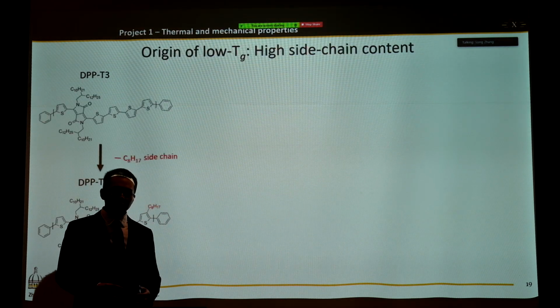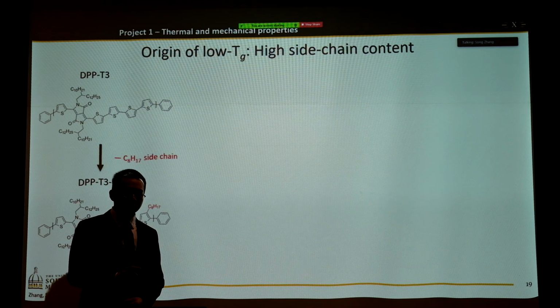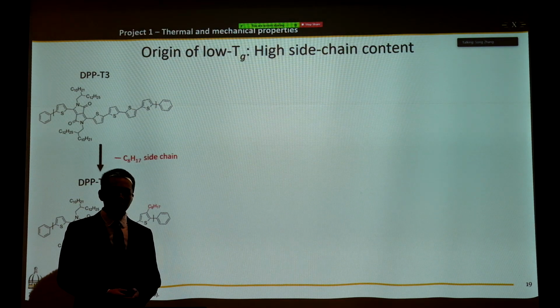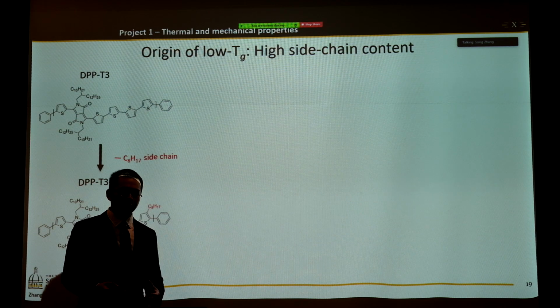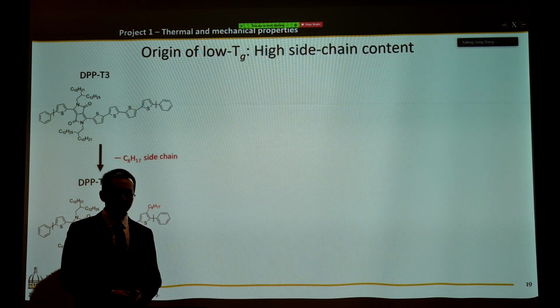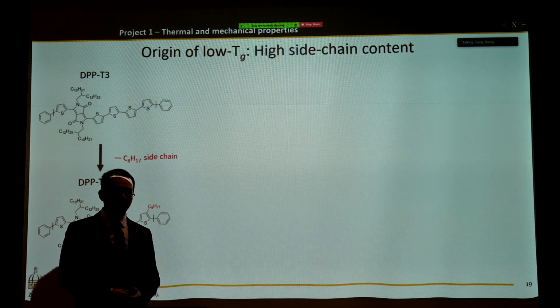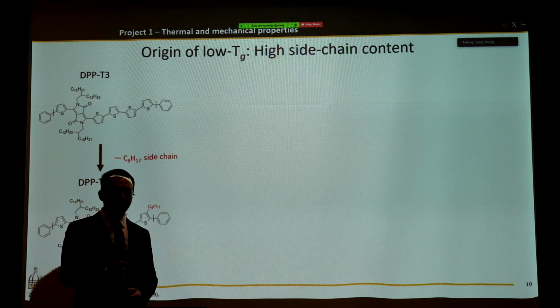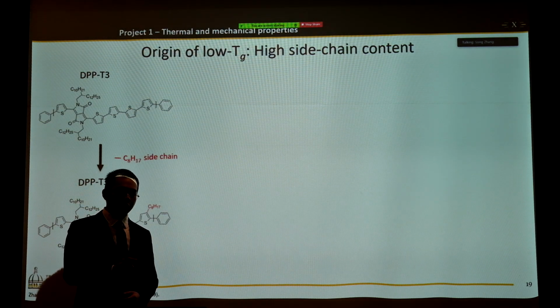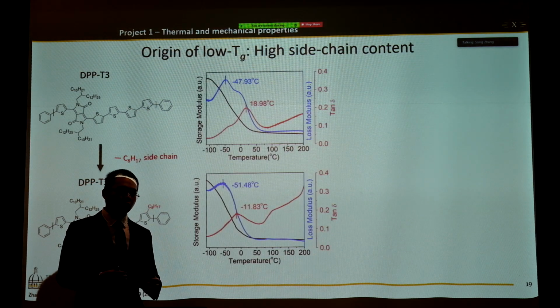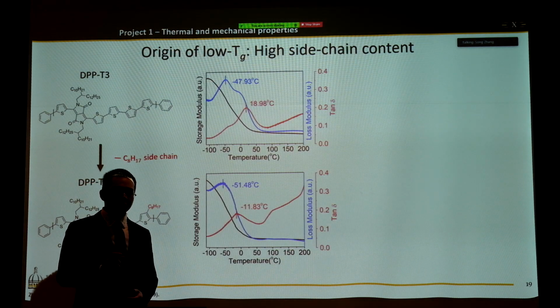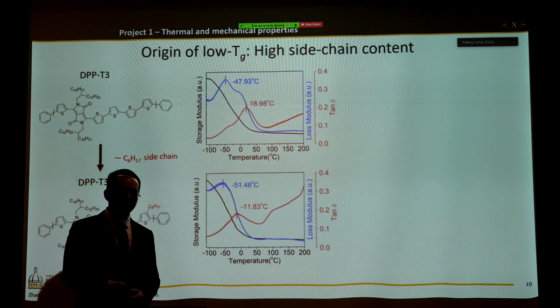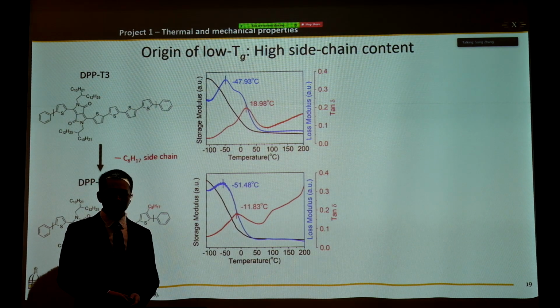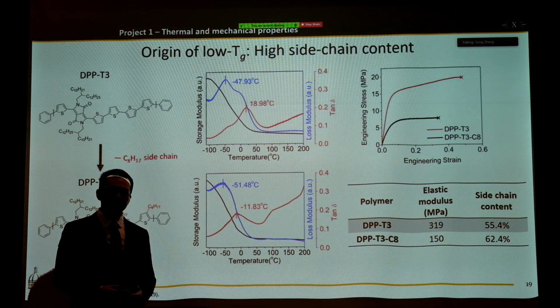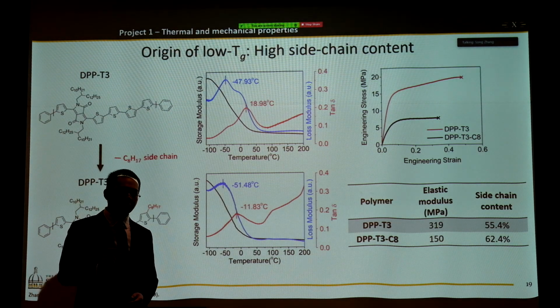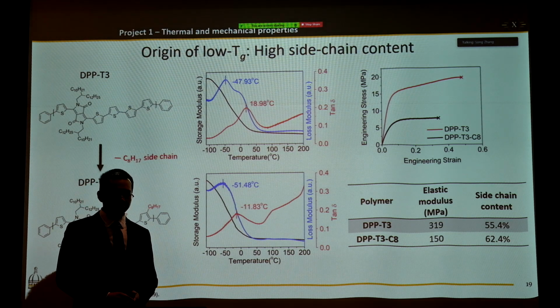Okay, now we identify the origin of low glass transition is from the side chain. So let's take a look at how the side chain can efficiently decrease the modulus and glass transition. Using a DPPT3 polymer as a model, we incorporated the C8 side chain onto the thiophene unit. And with that, we dropped the glass transition temperature by 30 Celsius degrees, from 19 to -12 degrees Celsius. And modulus can be dropped by more than 50% with only a 7% increase in side chain content.